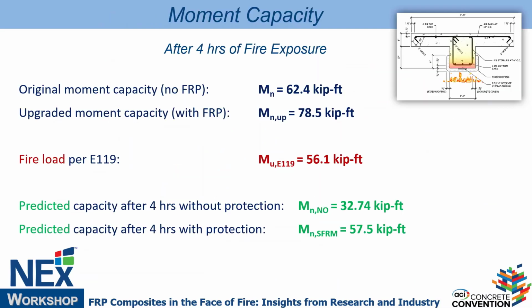This is from one of the beam tests, to give you an example. And again, I apologize, this is in US design values, but look at just the concept in here rather than the actual value. I had the original capacity, 62. With the addition of FRP, it was increased by 25% to 78. And then the fire load per E119 was 56, which we said corresponds to service. Service is roughly 70% of the ultimate, because if you look at the load combination in the US, 1.2 dead, 1.6 live, assuming dead equals live, the average is 1.4. So basically the service is 1 over 1.4, which is roughly 70%. Of course, if you have the ratio of dead load higher or lower, that affects this ratio.